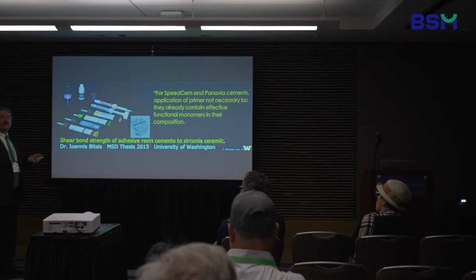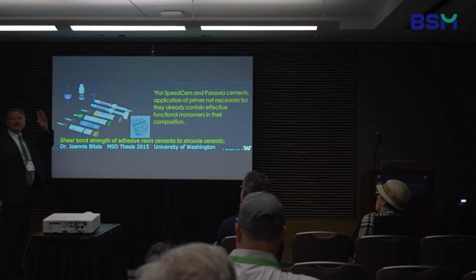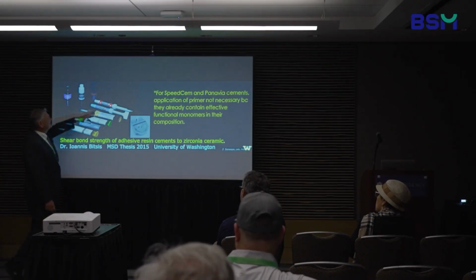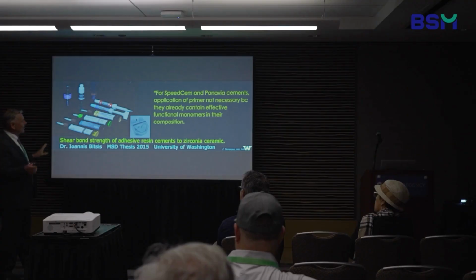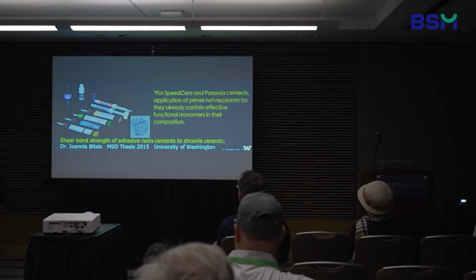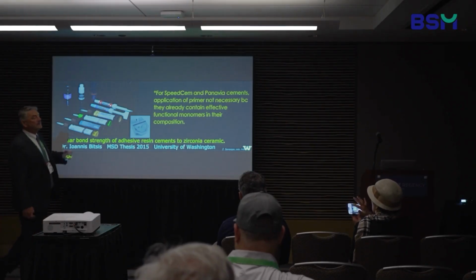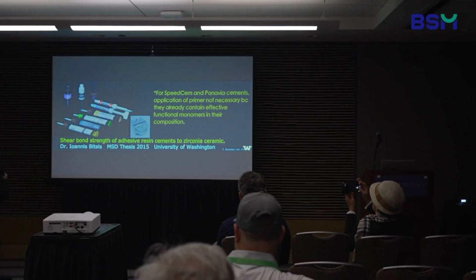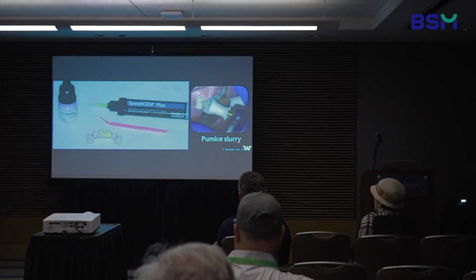I think I've done 4 studies now with tribochemical silicas, spraying it on there. Don't waste your time with it. But we found that of the major cements, 2 of them, SpeedCem from Ivoclar, which is a dual curing material, and Panavia, whatever, they change the name every year, but it's a great material. You do not need a primer. You have enough MDPs contained within the cement that it will give you adhesive bond strength to the ceramic.